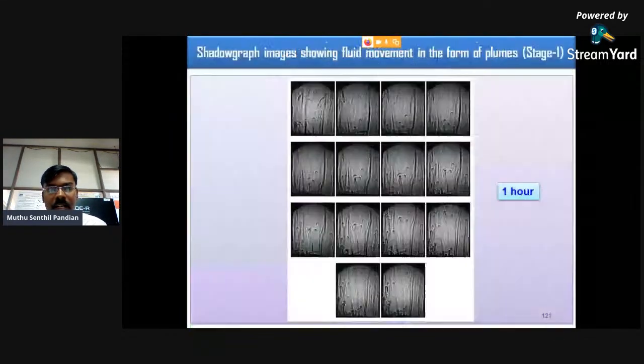So this is the convective fluid pattern of the SR method grown benzoin crystal. This is the bottom portion, and here the seed crystal is there. This is how the crystal grows due to gravity driven concentration. When we grow the crystals by the SR method, a small plume starts at the bottom of the glass sample. A plume is nothing but the movement of fluid flow from high concentration to low concentration. You can consider any one plume. This plume starts from the bottom of the glass sample, moves upwards, upwards, upwards, and finally disappears. Now new plumes start at the bottom of the glass sample.